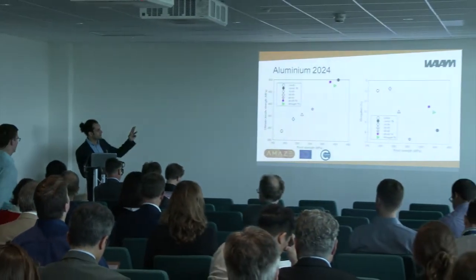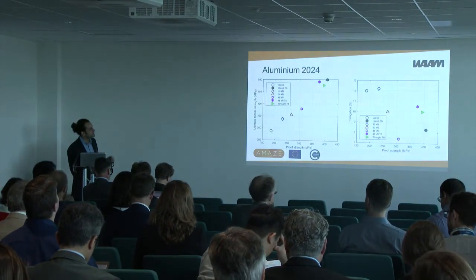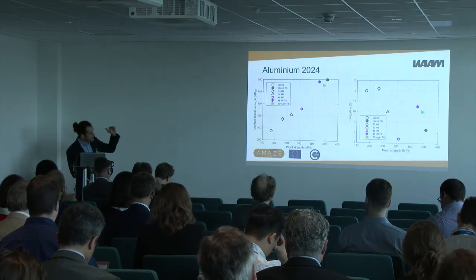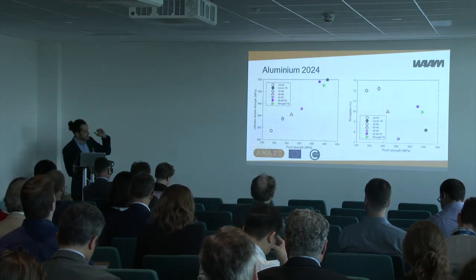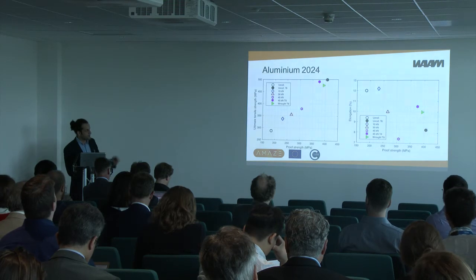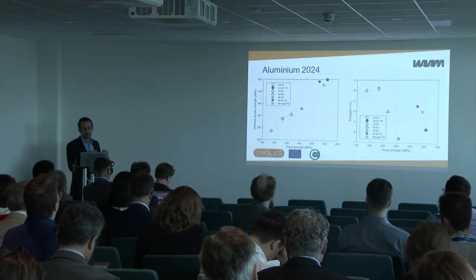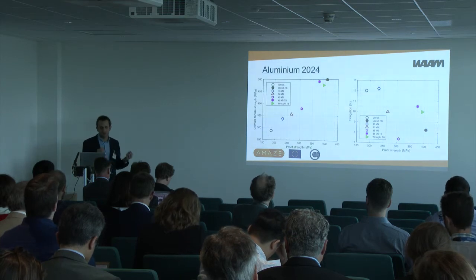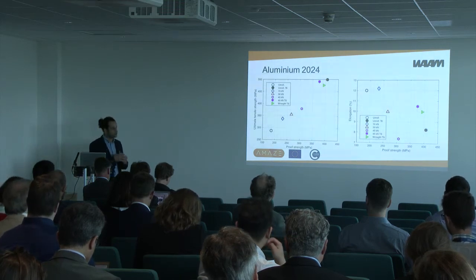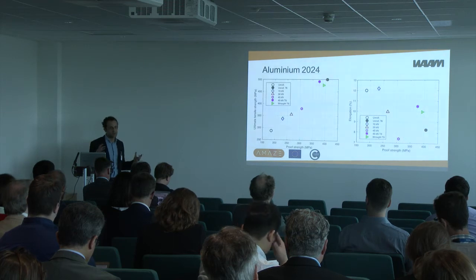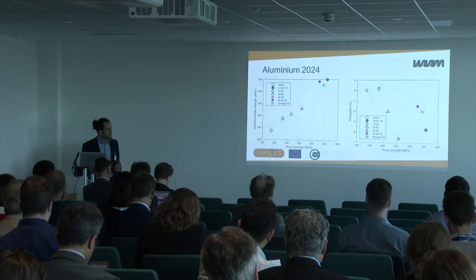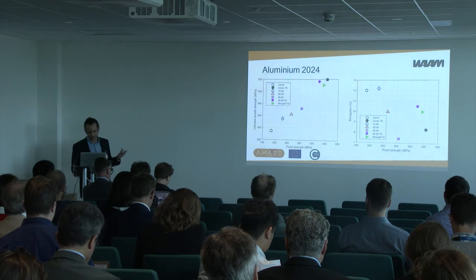And as you can see, similarly to the case of titanium, as you introduce rolling, the strength goes up, both the proof strength and the UTS. However, it doesn't quite get to the same level of the wrought alloy. The way we've got to get there and above is with the heat treatment. And okay, it's very nice to do heat treatments of this type on specimens that are very simple geometrically. Nevertheless, if you want to do this on something that is more complex, the chances are that you get distortion, you get cracking, and therefore, although it's good from an academic point of view, in practice, it might not be the best way forward.